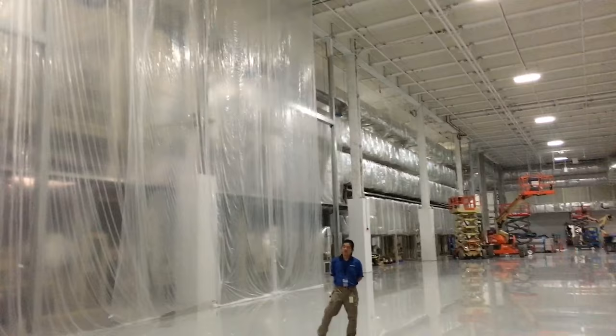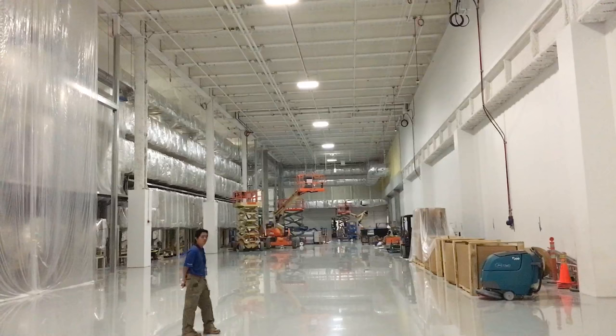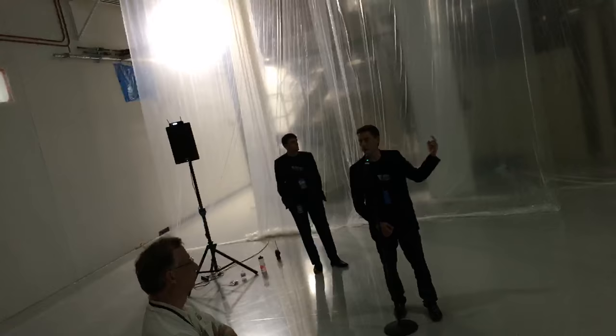metal substrate. So every one of these chambers has an air in and air out. As the air leaves, it's picked up a lot of this liquid solvent into the vapor phase. So all those outlet air ducts are routed together. And at the very end of the room on top, you see those large ducts going into the second floor through that wall. So right on the other side of that wall, we have the solvent recovery system, where we take all that solvent in the air and scrub it back out to clean the air. And then the air comes right back to the same oven in a closed-loop fashion. So this air never leaves the building.